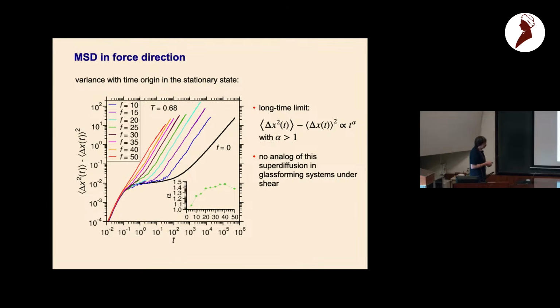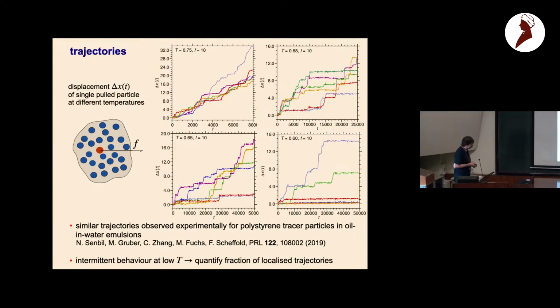So how do the trajectories look like if we go to the nonlinear response regime, where we have superdiffusion? These are typical trajectories from the simulation at different temperatures. Here relatively high temperature, 0.68, the example I've shown before, and then we go to lower temperatures, down to 0.6.